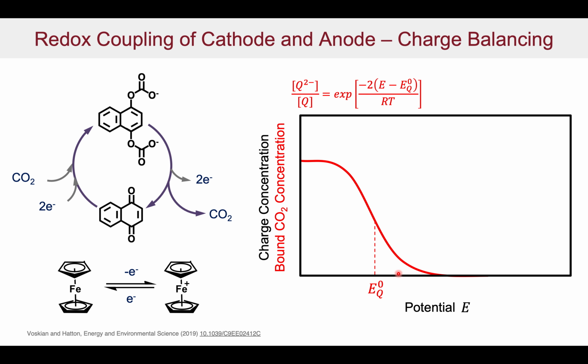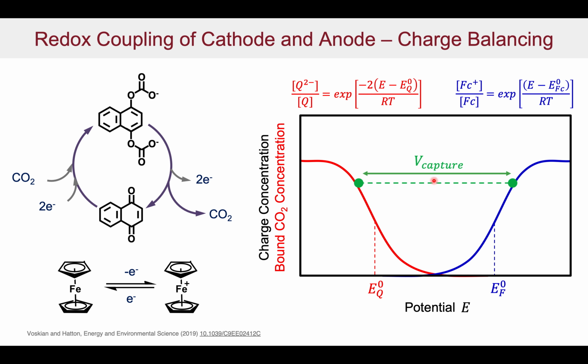By the same token, we also have the counter electrode, which is the ferrocene type electrode, as shown here, and this would be the actual charge concentration in the ferrocene electrode as a function of potential relative to its standard redox potential. Now what happens when you apply a voltage to the system is that it has to walk around and satisfy charge balancing. So when you apply a voltage, V capture, the difference has to be met, and the charges are balanced in these two systems.